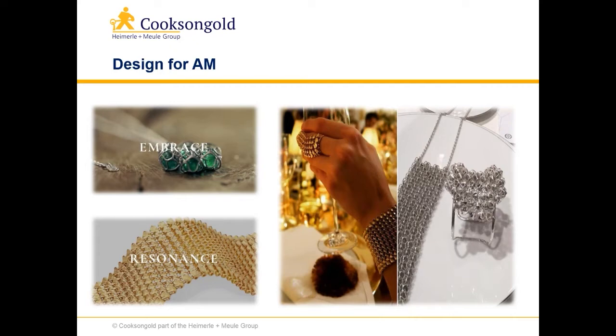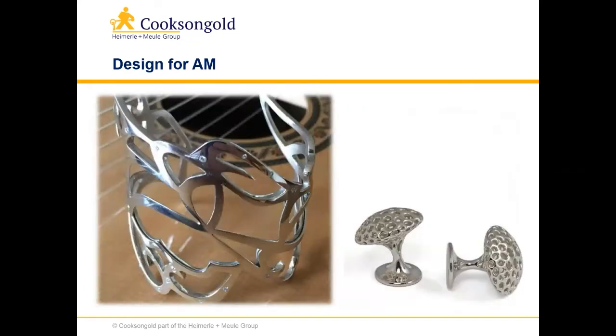But as I say, the guys will give you much better information on how we do that. So a couple of platinum designs, and I should say that platinum is by far and away the best material for the technology. It has a better density, and the densities in the gold and silver alloys are very, very good. They're probably higher than casting, but platinum is even higher in terms of density. The surface roughness is better also, and the print speeds are quicker.